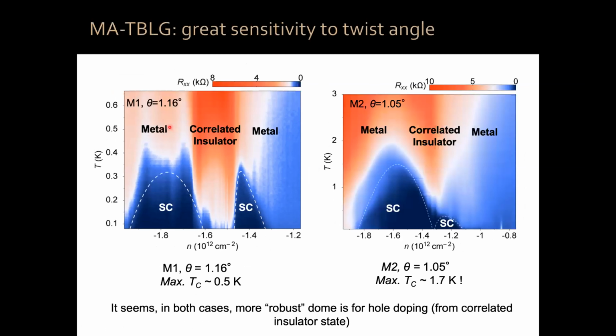Now, this is data for another device, 1.05 degrees with a higher TC. This one has a maximum TC of the order of 1.7 Kelvin. More often than not, we see this big asymmetric behavior between the dome for electrons and for holes. This was sort of the most symmetric we have seen it. Typically, the superconducting dome for holes is much bigger than for electrons.